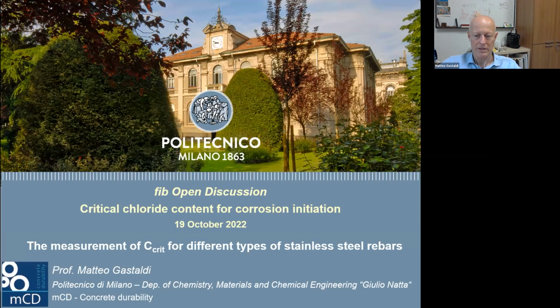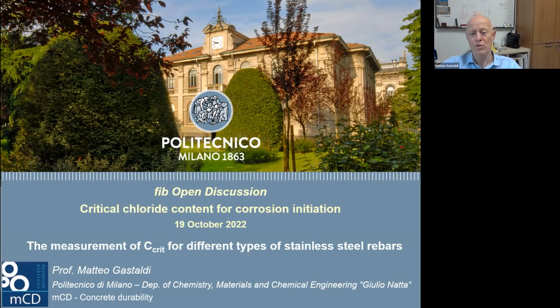And this is fundamental, I think. And second question is, I don't know much about stainless steel and its aggregation levels and the effect of saturation, but I did see somewhere that the stainless steel passive film requires oxygen to build up, and it just made me wonder whether the critical chloride level could be much lower below water because of the lack of oxygen. No, this is true also for carbon steel. It's the same.